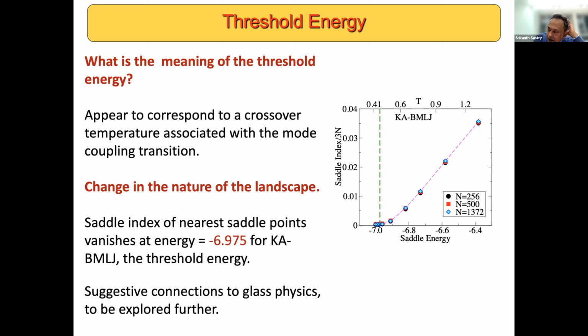Right. So, one thing that I did highlight to some extent is the fact that the mechanical deformation in a cycle of shear has as one primary consequence the formation of better annealed structures. Okay, so you could call it healing, and now in the limit that I'm studying, which is the athermal limit, there is no temperature, so the healing will not happen by itself. But presumably, if you do have finite temperature glasses, the aging dynamics will lead you to healing over time.